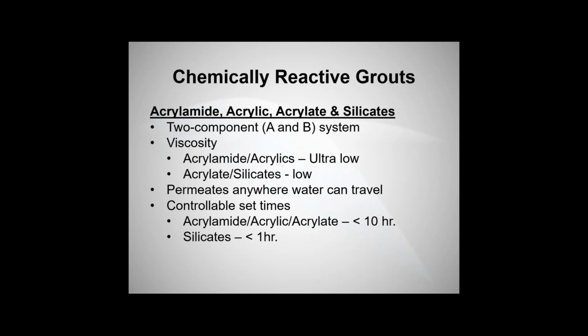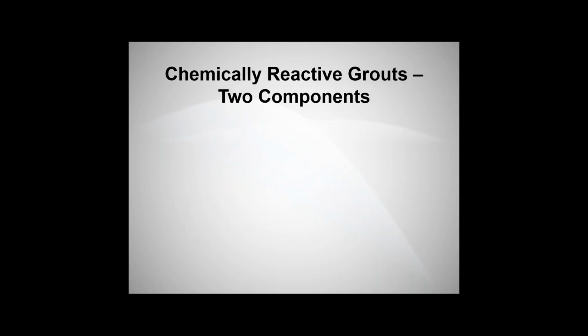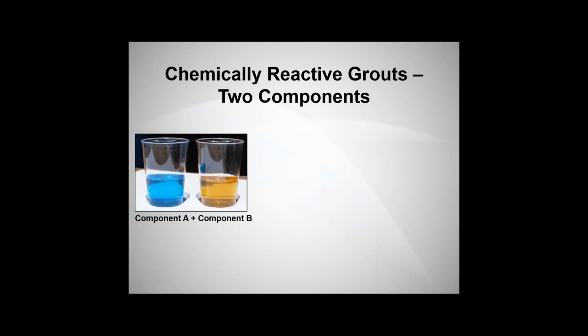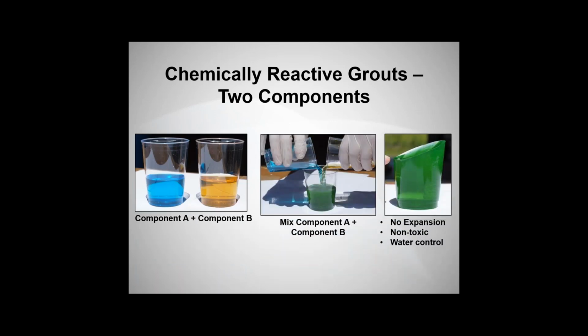Acrylamides generally, and acrylics and acrylates, upwards to 10 hours. I've seen it push beyond that envelope, upwards to 15. And then sodium silicates, roughly about an hour. So just a quick snapshot. Again, part A, part B, mix those together and you get a gelatinous material. Now this is a neat sample. Obviously this would be injected into a soil to create a permeation grouting application.